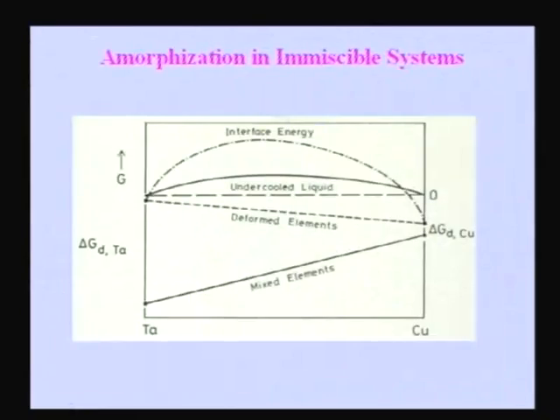And one can also have amorphization in immiscible systems. An immiscible system is like this. For example, if I take a copper tantalum system, it is an immiscible system, and if I take the tantalum metal and the copper metal, the free energies are given here. The free energy of the mixture is given by this line joining these two free energies, and the free energy of the amorphous phase is something like this, because it has a positive enthalpy of mixing and positive free energy of mixing. So the free energy does not go like this, but goes like this.